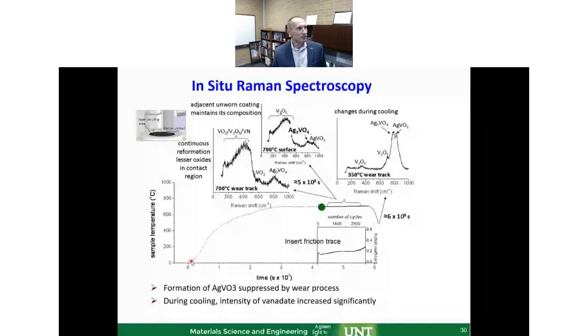But going back to the silver vanadate, you'll see that here as we're ramping up the temperature, and this is the sample temperature curve, we go all the way to 700 C in this case. Right at the green point here, we commit the test and start looking at oxides, and we are particularly tracking the formation of the silver vanadate, which will start appearing here through the peaks developed. And then we now have the answer why the friction is low. There's the friction trace here because we do have this double oxide.